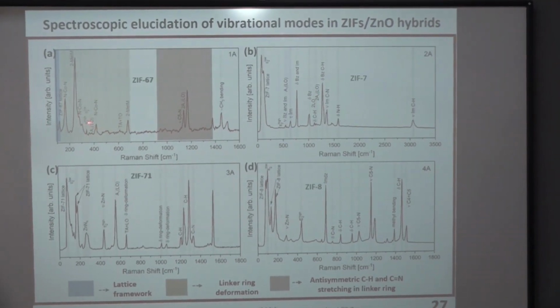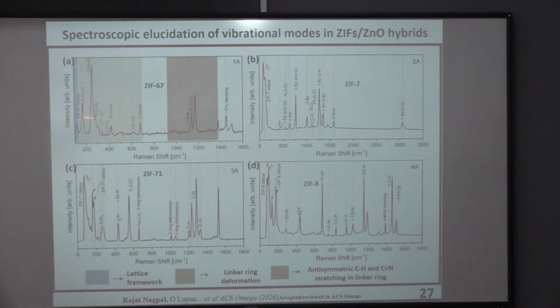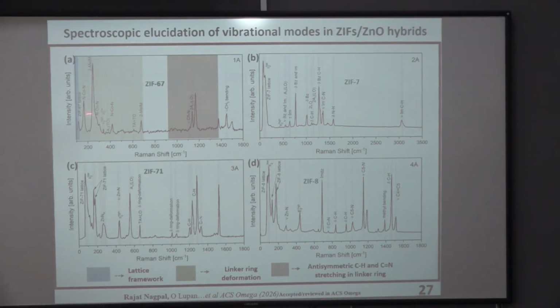Here we can see in this particular region, this is linker ring deformation. It also depends upon the intensity of the laser we are using. Firstly we tried high intensity, particularly for the ZIF-67 sample, and it was degrading a lot. This ZIF-67 framework, and this particular yellow regime based phonon mode, were restricting the intensity, reducing the intensity. So that's why we then tried to optimize the intensity.